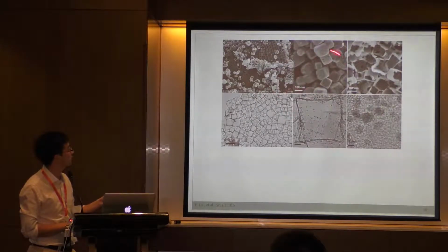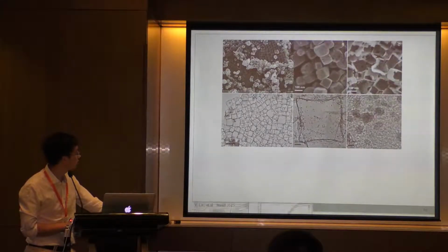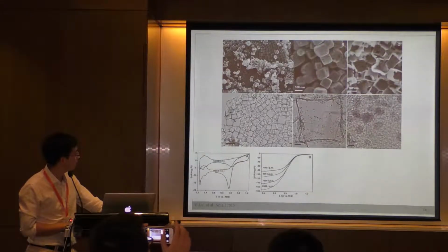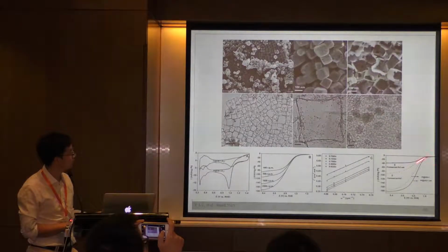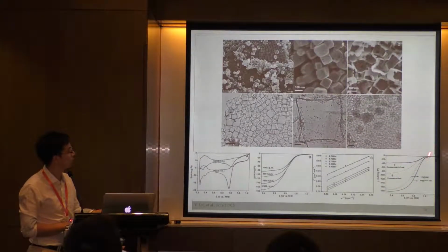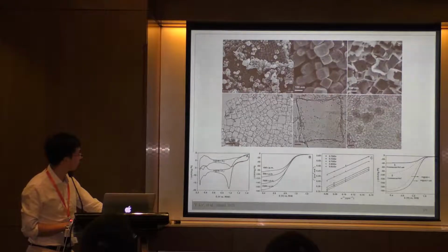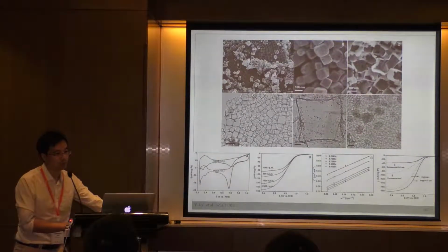So we can see the cube morphology of the graphene nanobox, and inside we can see very small platinum nanoparticles, about 1 to 2 nanometers. And we found this is even more active for oxygen reduction reaction. As you see here, it's much better than the commercial platinum catalyst. The activity or the current density, I'm not going to look into details here. Here I just show how we get this kind of nano-catalyst.